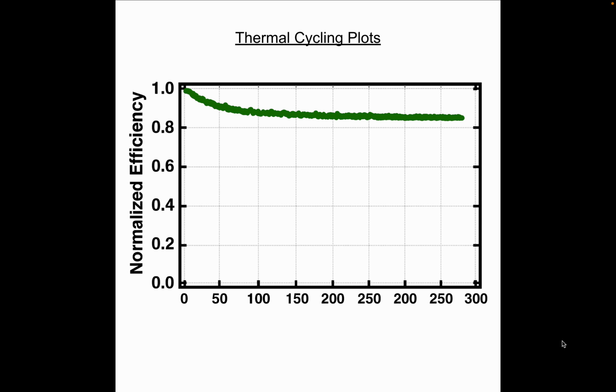And even more exciting, like I said, we updated the batches, we developed some better devices, and we were able to see almost 85% efficiency. So again, better than the 75%, better than we've really ever been able to see, and almost at the standards of just ground-based perovskite. So looking at this super intense, we went actually from negative 20 to 80 degrees Celsius here, hundreds of cycles, super intense light and temperature change, and we were able to actually identify immense amounts of success and retention that we hadn't yet seen before.